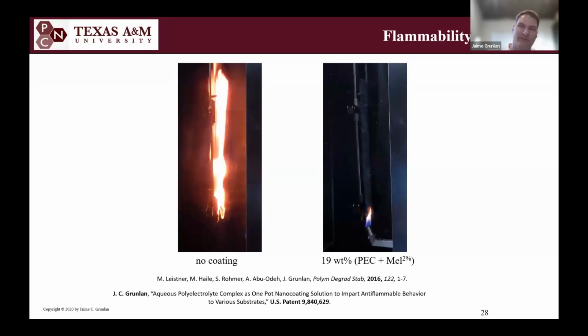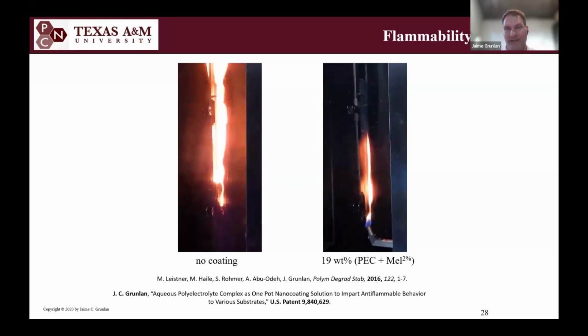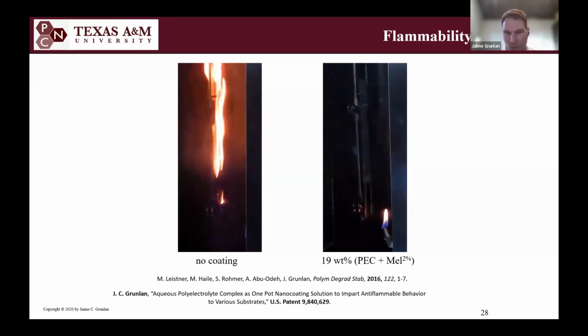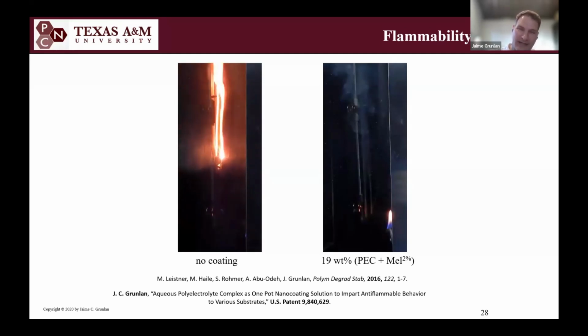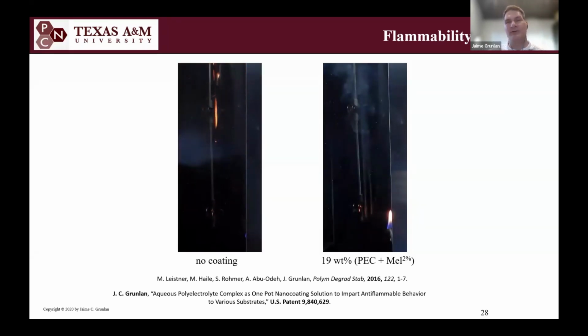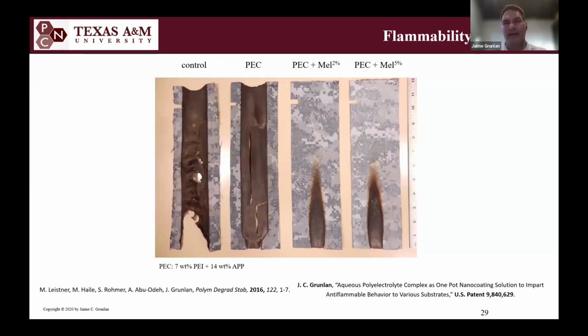And then we dipped that same fabric into a polyelectrolyte complex solution, and then into this 2% water-based melamine acetate solution. It created a coating that added 19 weight% to the fabric. That's a typical amount of flame retardant to add when you're making something flame retardant, although we have other recipes that are much lower. But anyway, this is an early example, and it worked very well. You can see we're passing the vertical flame test where we were not able to with the polyelectrolyte complex alone.